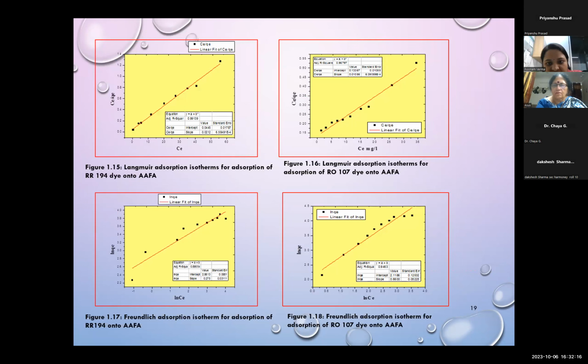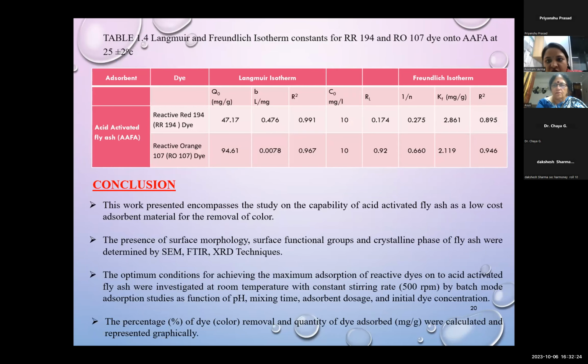And here is the graph for the Langmuir and Freundlich adsorption isotherms. From this study, we can observe that the Langmuir adsorption isotherm is more suitable and more favorable for the adsorption of reactive dyes on AAFA as compared to the Freundlich isotherm. From the table, you can see that the maximum adsorption capacity in the case of the Langmuir isotherm for reactive red dye is 47.17 milligram per gram, and for reactive orange is 94.61 milligram per gram, whereas in the Freundlich isotherm, it is only 2.8 and 2.1 respectively.